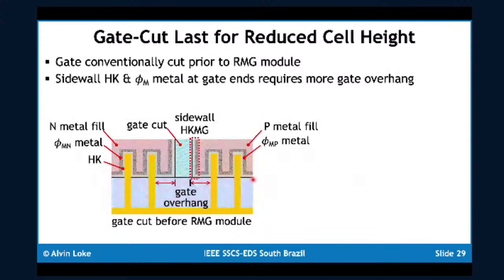The gate cut last is also another DTCO trick that's used. The idea here is that typically we would cut our poly way in the front end, which then, when we use the replacement metal gate integration, requires that you have sidewall HighK metal gate deposition. Well, having this increases the gate overhang between, say, an NMOS and PMOS in a standard cell.